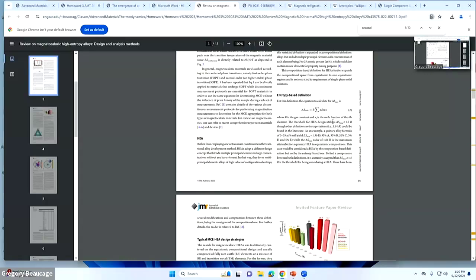That's going to be the mole fraction of red times the log of the mole fraction of red. So this is just weighting each component, the prefactor, and ln of the mole fraction is the entropy. R ln x is Boltzmann for the entropy, right? So that's just from Boltzmann's law. And then this x prefactor is because you're going to have 5 components, so the total is going to be the fraction. The x fractions of each one sum to 1, and each one is modified by the entropy of that one, which is R ln x. So it ends up x ln x.